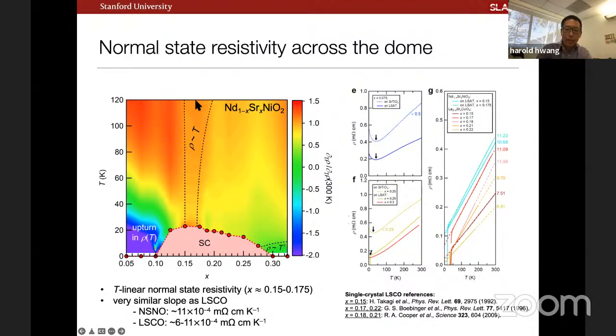So what I'm plotting here is the derivative, the slope of the resistivity, normalized to the room temperature value. This orange region is where the slope is the same across varying temperature. And so we have this narrow sliver of approximately T-linear resistivity. I show that here for these two samples near this regime. These light blue curves are the resistivity as a function of temperature.